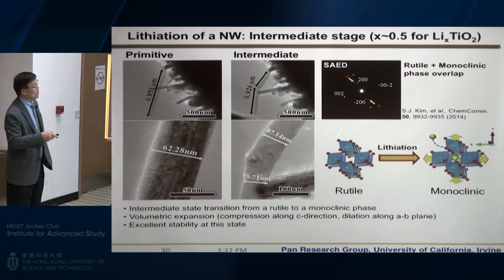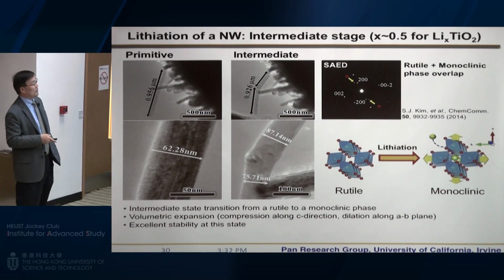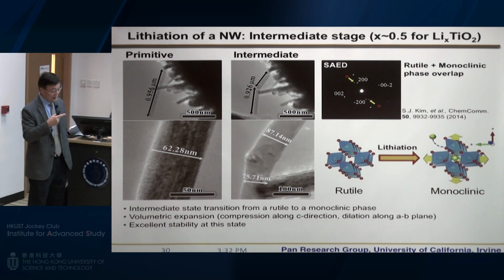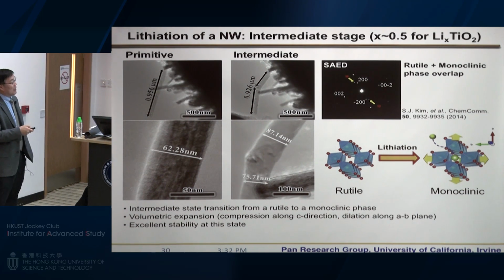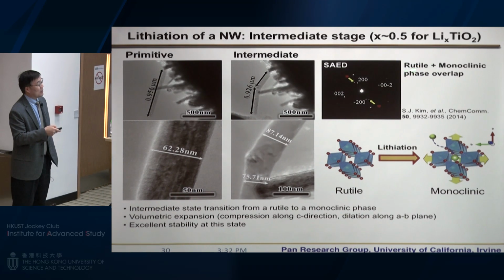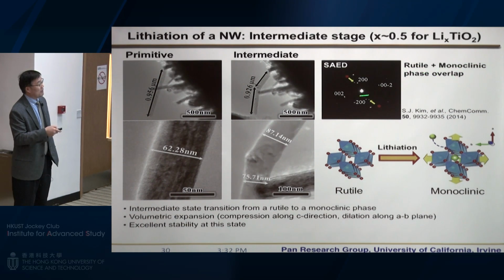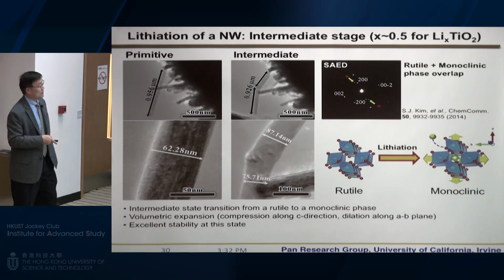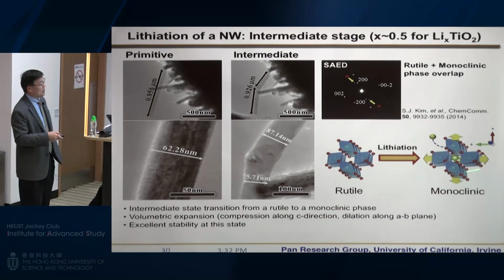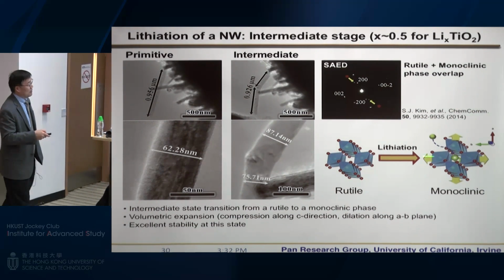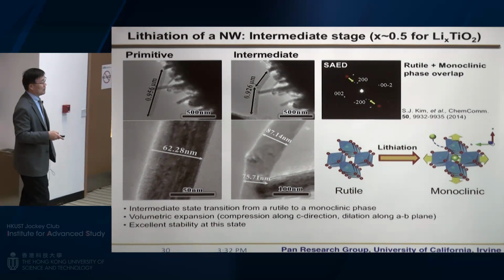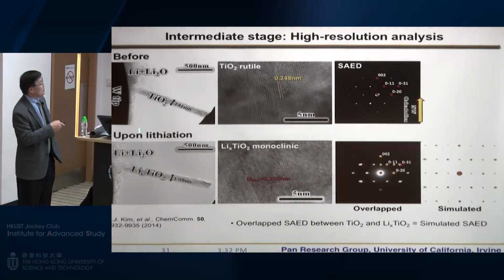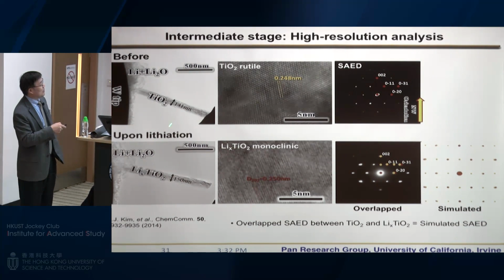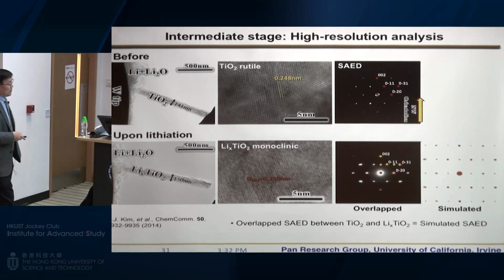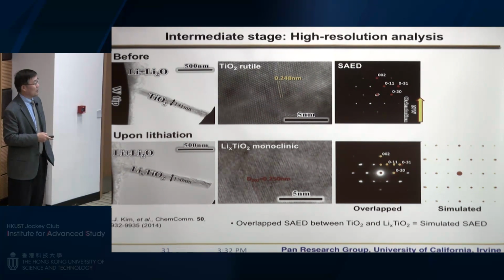So Sangju did all this quantitative analysis, and this change has two steps. The first step is a transition of TiO2 from rutile to monoclinic. This can be easily determined by electron diffraction. This is a so-called intermediate state where the lithium gets in, but it is not fully lithiated. Then we did further analysis of what happened during this transition from rutile to monoclinic. You can use electron diffraction. You can also use high resolution imaging to confirm this.